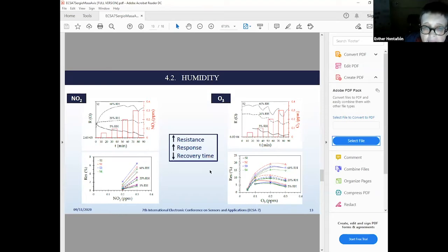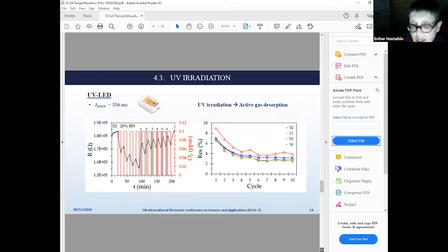So we can say that the effect of humidity is to increase the resistance of the sensor, to increase the response of the sensor to the two gases, and to reduce the recovery time of the sensor. Still, we investigated the possibility to reduce the recovery time further by illuminating the sensor with UV irradiation coming from an LED source. We found that indeed the UV irradiation has a very positive effect, because it was possible, by optimizing the time the UV light illuminates the sensor during the gas desorption phase or sensor recovery phase,